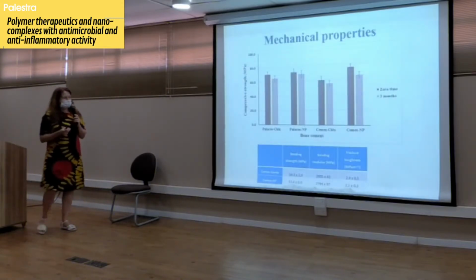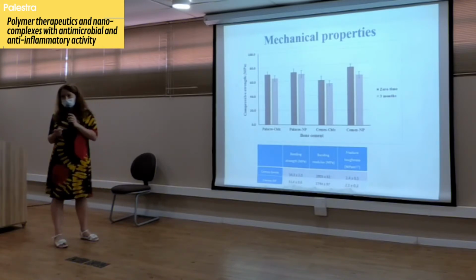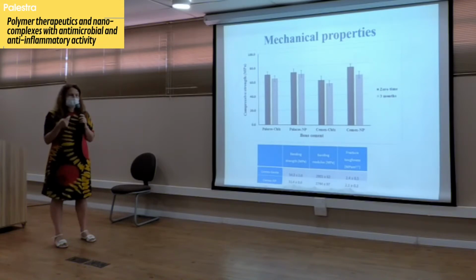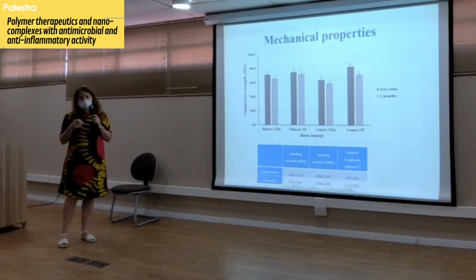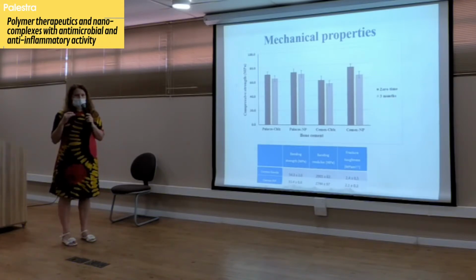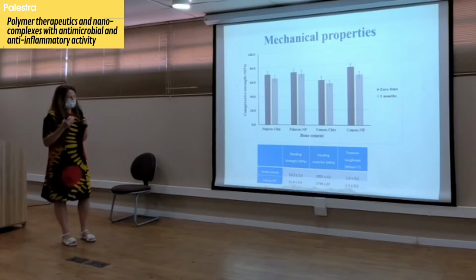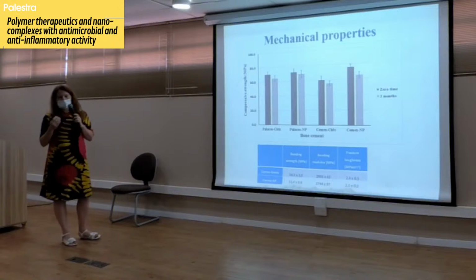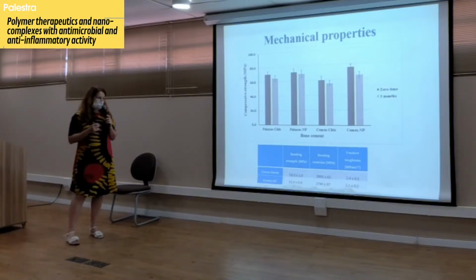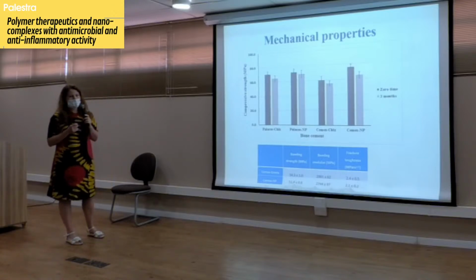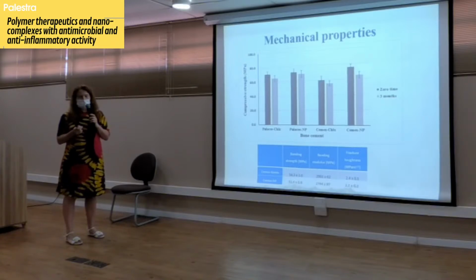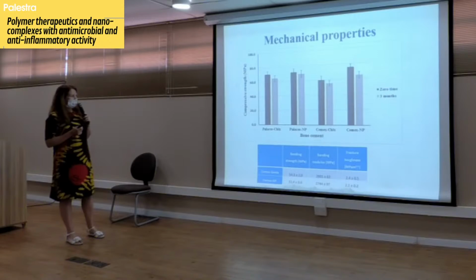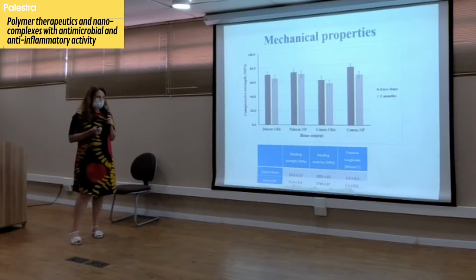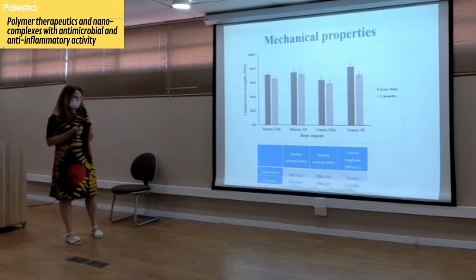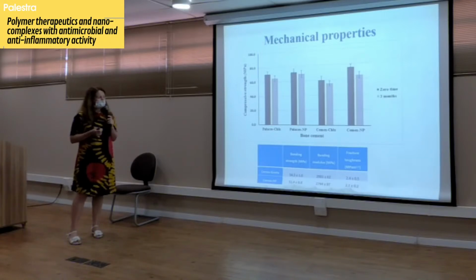And the next testing which we did is looking at the mechanical properties. So remember in the beginning I told you that you can have wonderful antimicrobial activity in your bone cement, but if mechanical properties are not within the standard, we use the ISO standard, so it has to be within 20% variability maximum from the commercial formulation, this cement will never be used in clinics, because mechanics is very important for load-bearing operations such as knee or hip. We looked at the compression strength, the bending strength, bending modulus, and fracture toughness. We measured all these and compared them with the commercial formulations. And it was in good agreement, within the 20% difference. So we're very pleased with that.